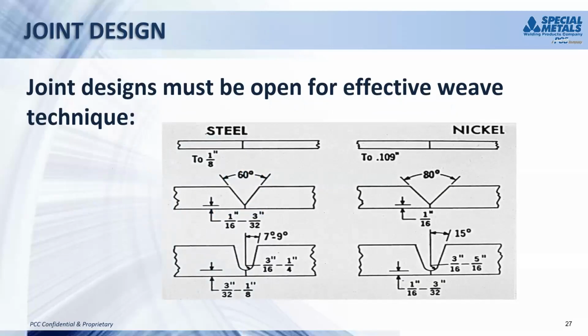So next slide. And this is what I was referring to before. The joint designs for nickel alloys must be different from steel. You notice that we've opened the included angle up from 60 for steel up to 80 for nickel alloys. And that gives you room to be able to weave the electrode appropriately. And if you look at the U-groove in the bottom part, we've opened up the groove, and you notice the land for nickel alloys is not as thick as it is for steel because of the penetration differences. Next slide.